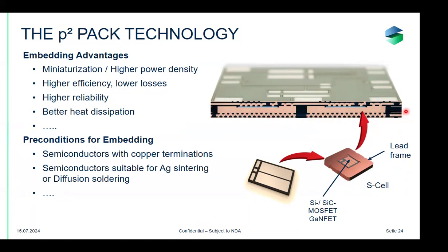And what you see here on the top is a cross-section through a half-bridge construction of such an embedded device. You see one device on the left side, one device on the right side, and you see connections to the source of the component. You have the gate contact, and you also have a contact to the drain. As the lead frame is representing the drain contact, you can now take the drain contact from the lead frame, which is another advantage because by doing this, you can create very low switching loops. And as you have the interconnection from the drain to the source, you can see this here is your middle point of a half bridge. So this would be the phase contact or the phase out, the AC out for a half bridge construction. Again, you see the source contacts, the gate contacts, and the drain.